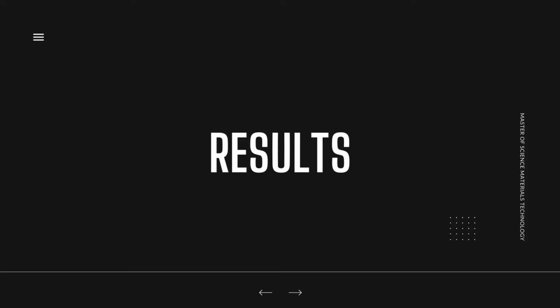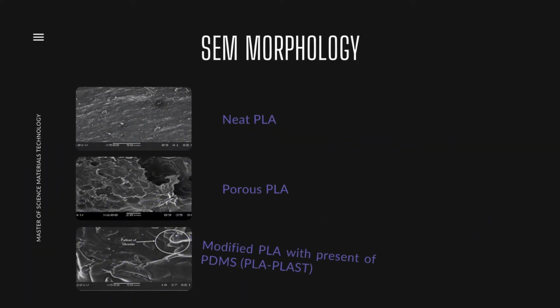For the result, we are going to show the tensile test, SEM morphology, and also structural change of PLA-PLAST from porous PLA. SEM morphology. For the neat PLA, it shows clear and clean surface that undergo brittle failure. For the porous PLA, it can be observed that NaCl content has been removed out from PLA matrix and left the PLA to become porous.